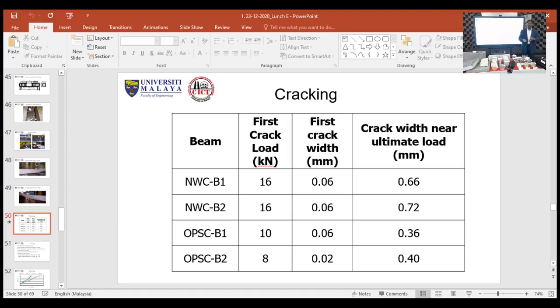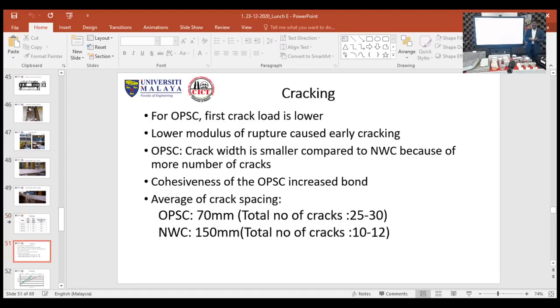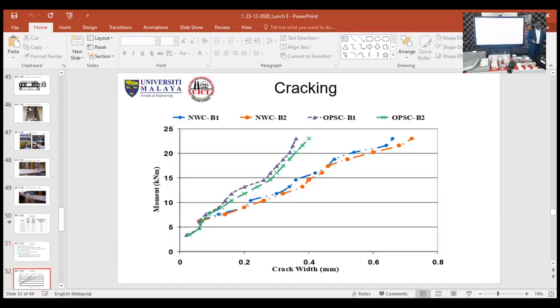We tested two beams, identical beams, to compare the structural performance. The total number of cracks in the normal weight concrete is only around 10 to 11 cracks, whereas in this oil palm shell concrete beam, it was more than 25, around 30 cracks. So that shows the more the number of cracks, it shows the bond, it shows the ductility, and the number of cracks opening up shows the ductility of the beam. And we can see the development of the crack over the loads and moment, and also the deflection criteria.